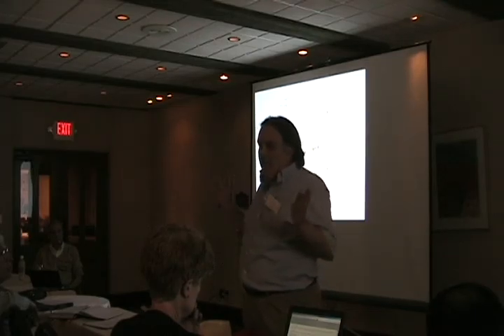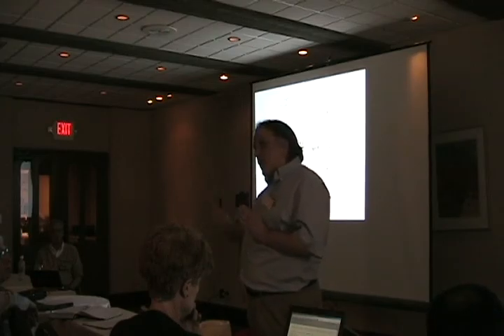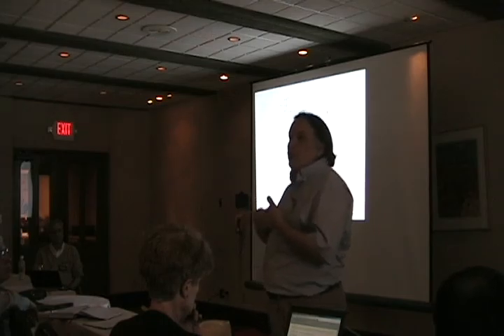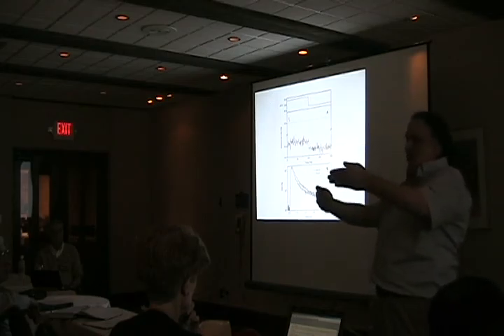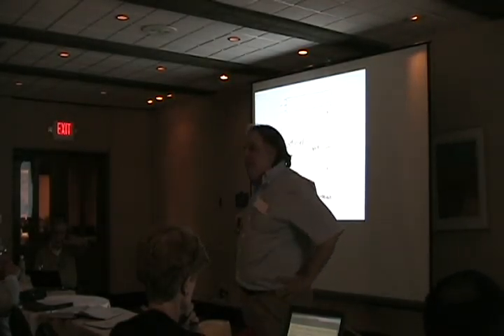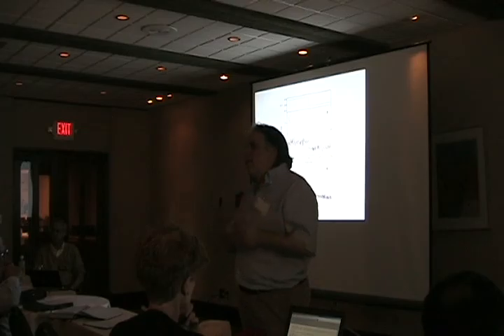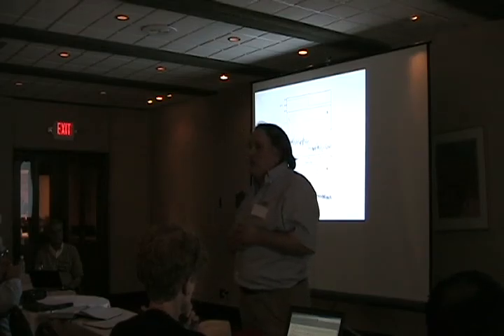Okay. In the electrochemical devices, you can go to anything you want. That's the amazing thing about electrochemistry. You can scan the potential plus or minus 10 volts. But you better not scan it past the point where the electrode gets reduced to indium metal and so on, because at that point the electrode just leaves the glass and goes into solution. So when we go to negative 1 volt, we strip the indium off. Although we've got a new way of doing it using gold electrodes. We thought that was just great until the gold didn't work. We were unaware of this. Gold's a very complicated material. I thought it would be really straightforward. Gold is very complicated, especially nanostructured gold. So we'll eventually get it to work.